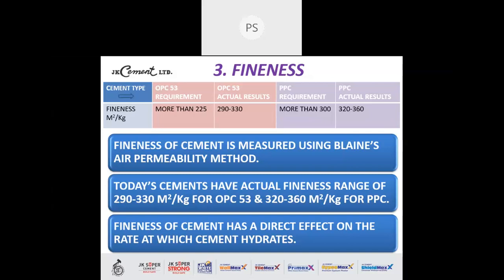Fineness of cement has a direct effect on the rate at which cement hydrates. Finer the cement, because the surface area is increased, faster will be the rate of hydration of the cement and vice versa. But up to a certain limit, if the fineness increases after that limit, it will have an impact on the water requirement of the cement, and you will face more water required for the concrete, and that may reduce your strength also. So an optimization in the fineness has to be done.